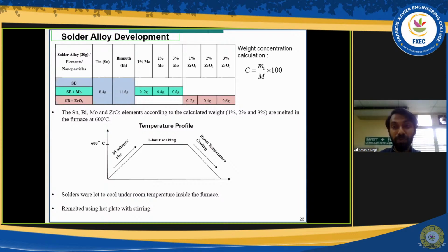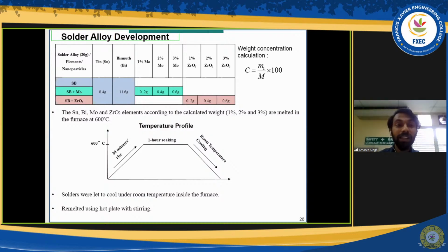So this is my process. I've weighed it accordingly. I've used 1%, 2%, and 3%. Like I said, we don't have a standard. I can't say 2% will be the best, or 3% will be the worst. I have to investigate. So I've used 1%, 2%, and 3% for both nanoparticles, and they were melted together in a furnace. This is the temperature profile. At 600 degrees Celsius, all these materials will be added: tin bismuth with molybdenum separately at 1, 2, and 3%, and tin bismuth with zirconia at 1%, 2%, 3% separately. Then we let it cool.